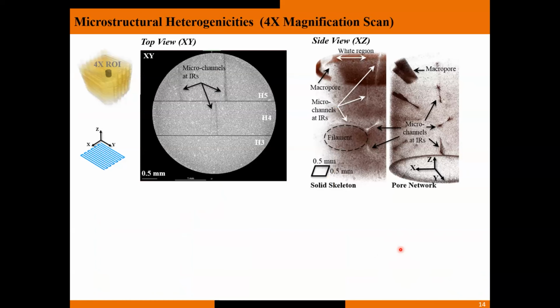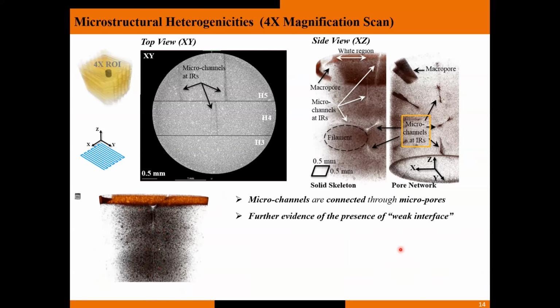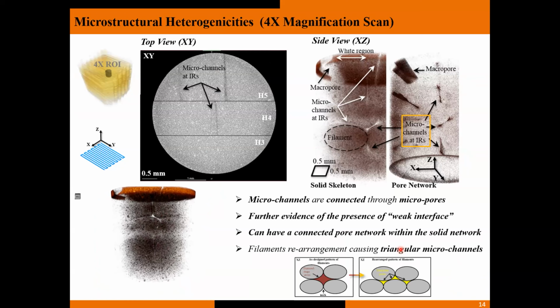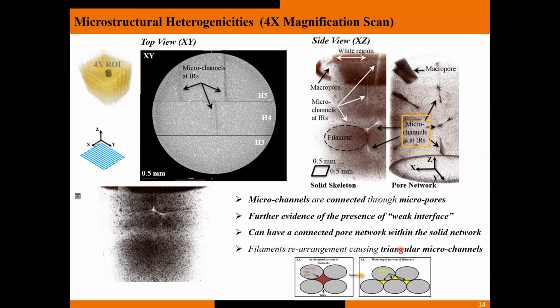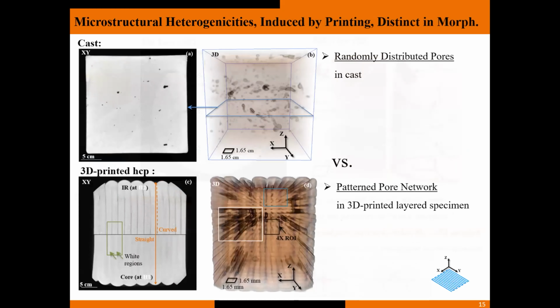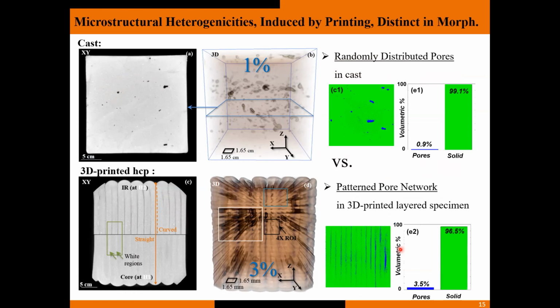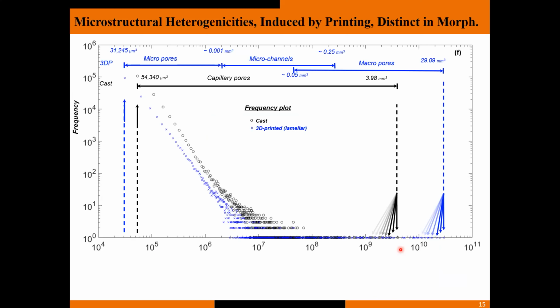So we looked into a smaller scale resolution, and what we found was that these microchannels are actually connected through one another in micropores, which was evidence for the presence of a weak interface. And then we also noticed the rearrangement from some type of a diamond shape microchannel to a triangular shape, which is visible in the video. So we later quantified these using a method called K-means clustering, and compared them to the reference cast. So the 3D printed samples typically not only had higher degrees of porosity volumetrically, but when we did the segmentation, we noticed that the arrangement or the morphologies are also fundamentally different. As you can see here, the porosity induced by printing is distinct in the blue, the printed samples. We have macropores, microchannels, and micropores, whereas in the cast case, you have a continuous spectrum of porosity.